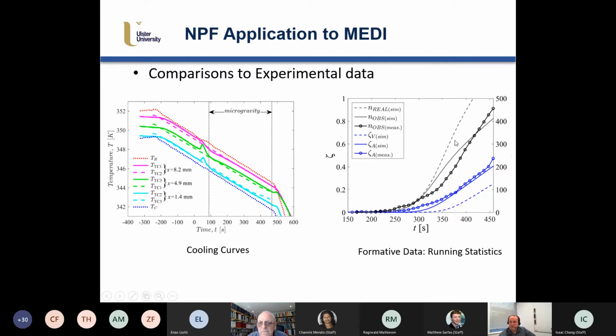So reasonable agreement, and then you see what couldn't be measured. Here the model is able to predict what the number of real nucleation events were in 3 dimensions. So that includes the ones that were unobservable. Looking then at area fraction in the blue curve. The simulated area fraction here is the solid blue line, and then the white circles are the area fraction that were measured, and reasonable agreement, I would think, to quite good agreement. And in particular here, then you see the volume fraction. Now, volume fraction is always an underestimate of area fraction, and the number of real nucleations in 3D is always greater than the number of observed.